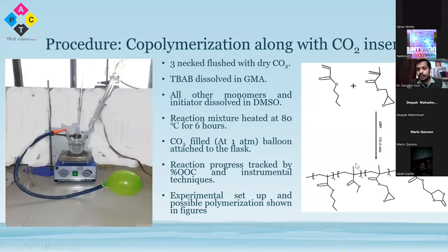When we carry out the reaction, the four units are obtained in the polymer chain. The three are as it is, and the fourth one is because some of the glycidyl methacrylate monomers were converted with the five membered cyclic carbonate groups. So in this way, we can incorporate the cyclic carbonate group in the conventional polymer system. All this reaction was carried out at the normal atmospheric pressure, slightly above 1 atm of the CO2, and the reaction was performed for 6 hours at 80 degrees Celsius.